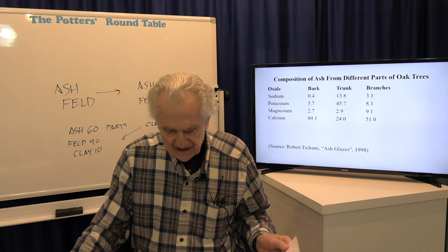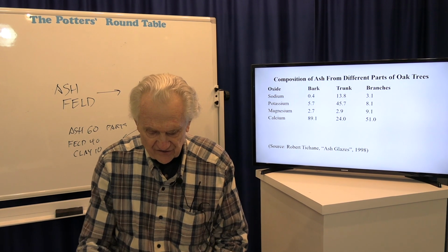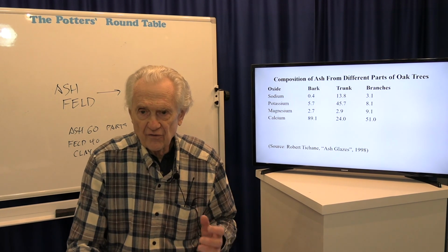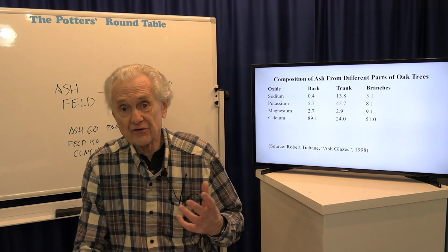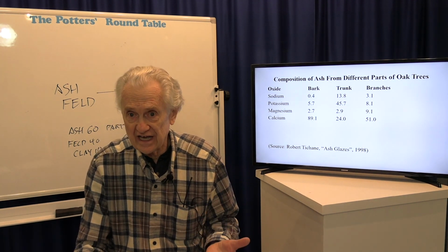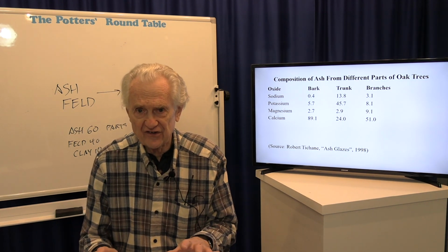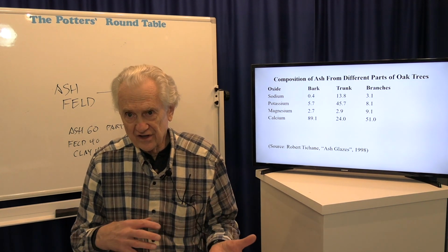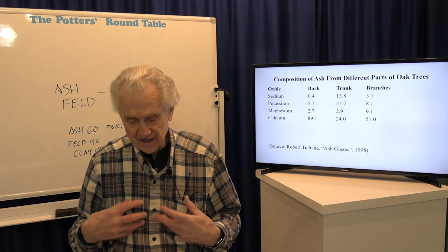Adjusting or altering glazes. If you make up a glaze and you like the looks of it, but let's say it's a little runnier than what you'd like, well then you could, just like with any other glaze, increase the alumina or increase the clay, or decrease the fluxes. Since now you have all the ingredients at hand, you could change the recipe either way. You could add more clay, or you could reduce the fluxes to make it less runny.